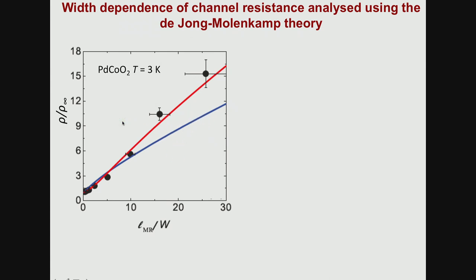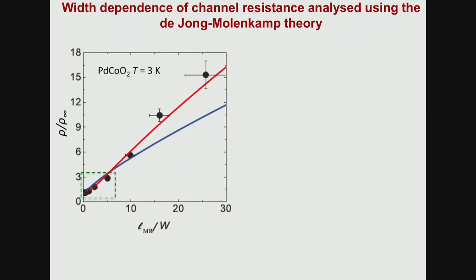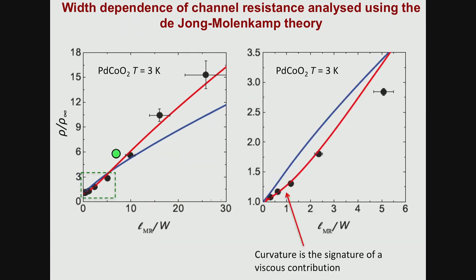That in itself isn't so impressive, but it gets a little bit better when you consider the blow-up, because the hydrodynamic prediction, as I'd said before, is of some upward curvature at low widths, followed by the hydrodynamic prediction crossing the ballistic prediction at high width, and at very low widths it crosses. We see all of that. We see the curvature, we see the crossing point around the expected result, and we see the different values for the very low width wires.